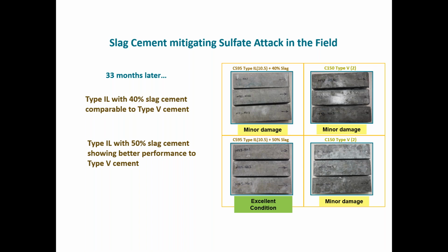So what I wanted to reinforce is that what they observed from this after 33 months was minor damage for all of the samples except for one. The two type 5 samples had minor damage in the sulfate environment. The IL with 40% slag had minor damage, so it was very comparable. And then the IL cement, which I should probably explain, is a blended cement that is limestone, and the 10.5 represents the amount of non-calcined limestone. So it's an addition to the finish mill. But at 50% replacement of slag, it actually performed better within this 33-month time period than the type 5 cement. So that's a very impressive example.